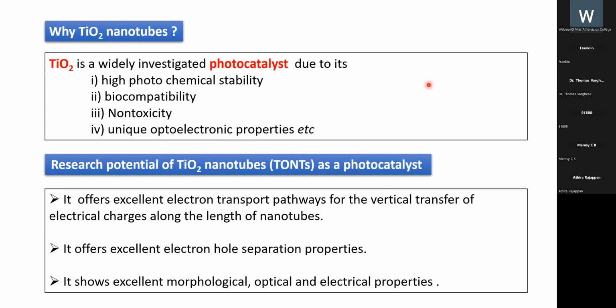Semiconductors such as titanium dioxide, zinc oxide, iron oxide, etc. all act as good photoactive materials. Among these, TiO2 has proved its benchmark as a good photocatalyst due to its high photochemical stability, biocompatibility, non-toxicity, unique optoelectronic properties, etc. Among various nanostructured forms of TiO2 like nanoparticles, nanorods, nanofibers, etc., the research potential of the one-dimensional nanotubular structure is significantly high since it offers excellent electron transport pathways for the vertical transfer of electrical charges along the length of the nanotube. It offers excellent electron-hole separation properties. It shows excellent morphological, optical, and electrical properties.